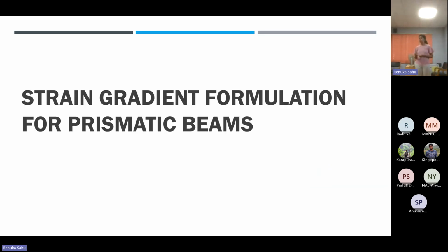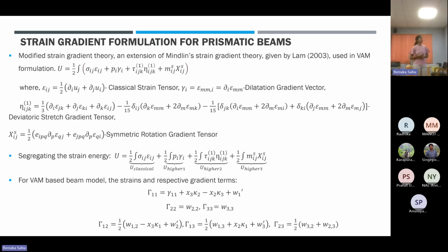Now we come to the strain gradient formulation for prismatic beams. As discussed previously, the modified strain gradient theory is an extension of the Mindlin strain gradient theory given by Lam, and this is what we use in our variational asymptotic formulation. We have the strain energy definition, where we have the classical strain tensor, dilatation gradient vector, the deviatoric stretch gradient tensor, and the symmetric rotation gradient tensor.